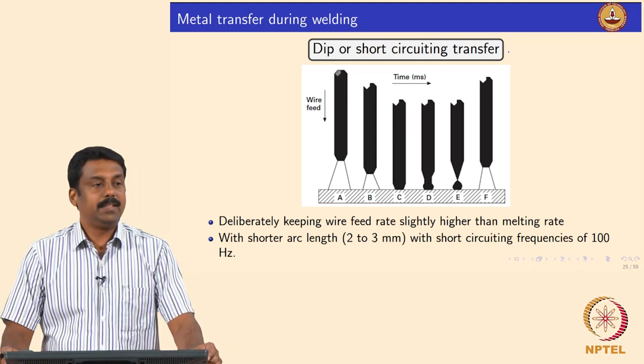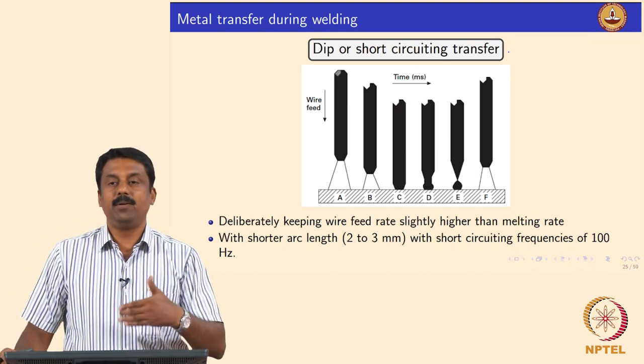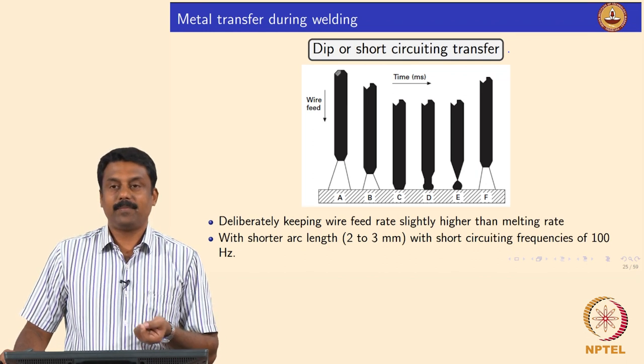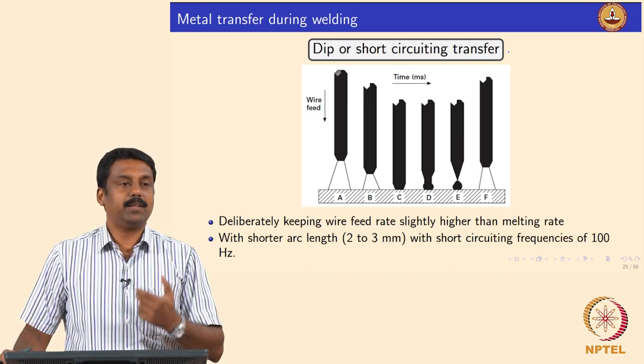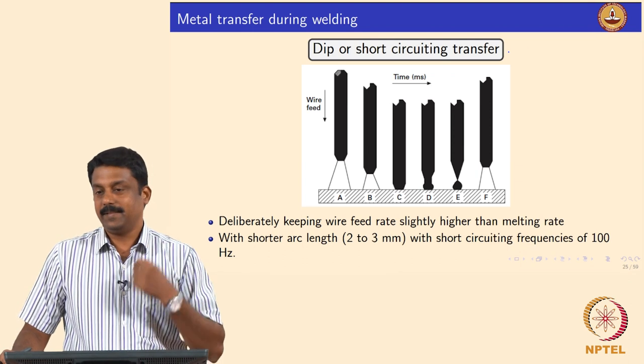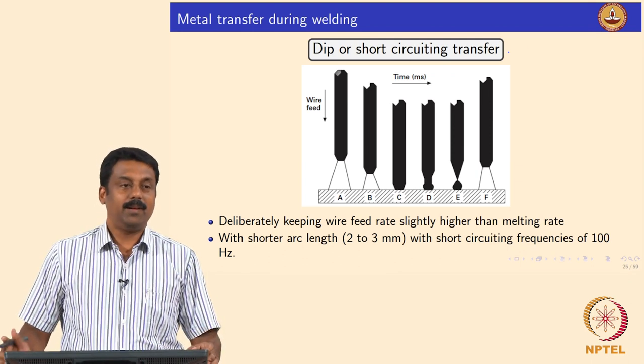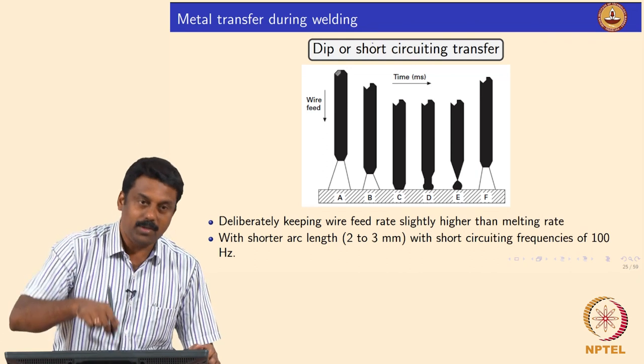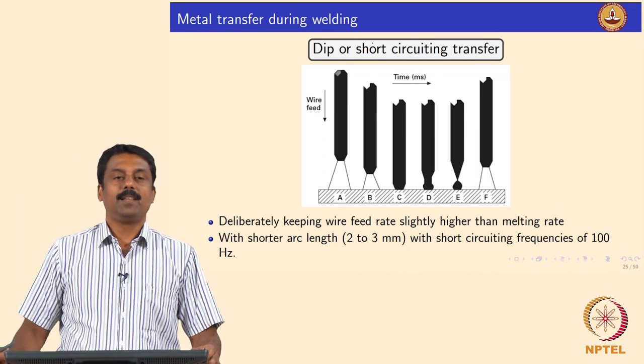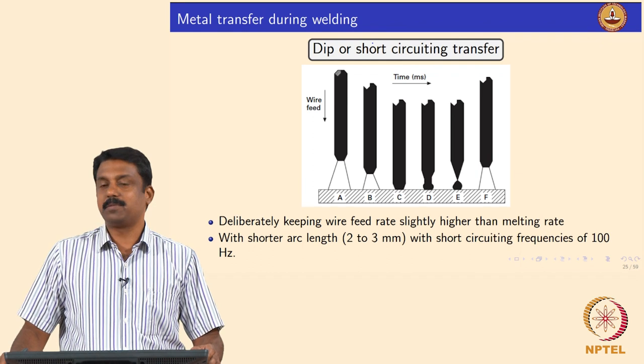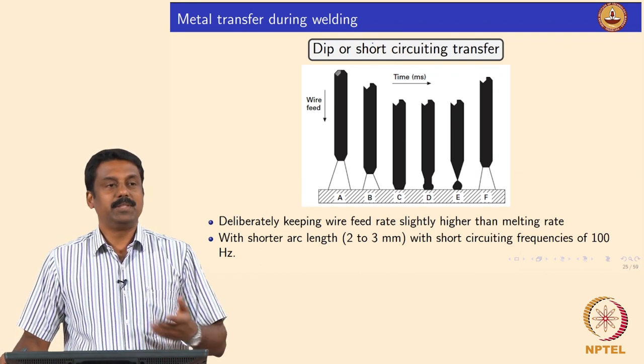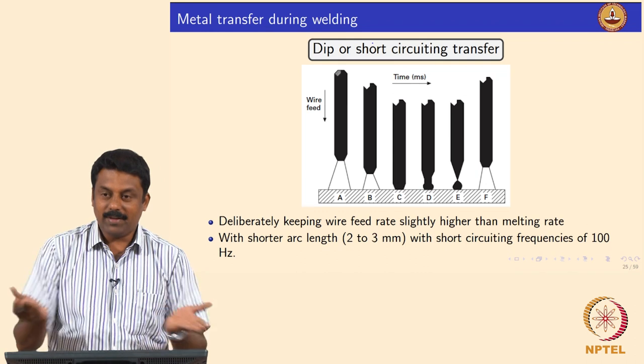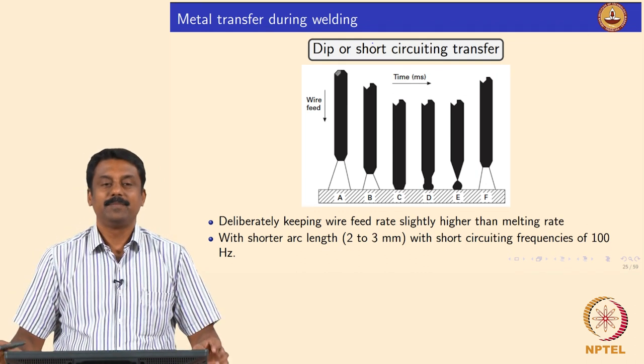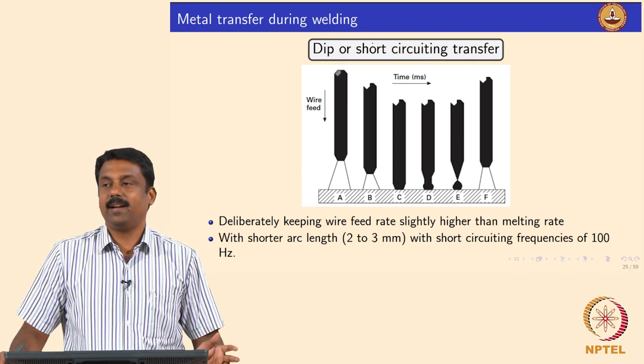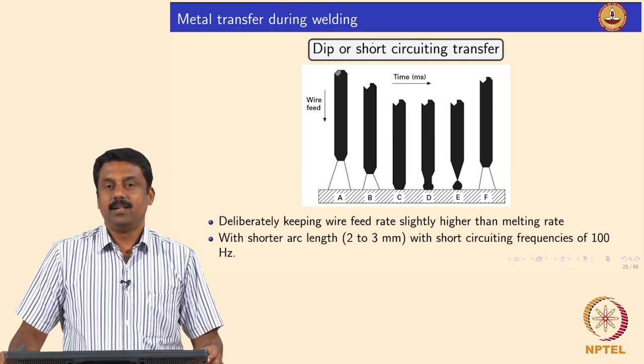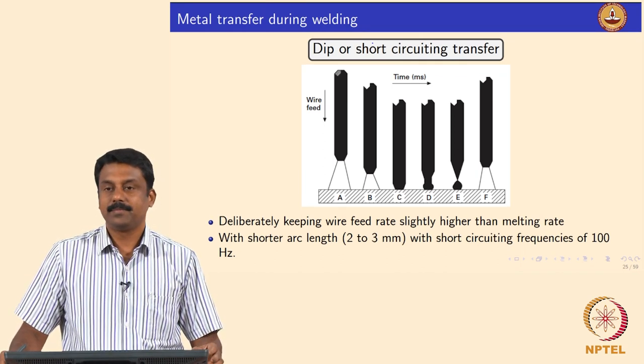So, the other mode of transfer. So far we looked at free flight transfers, and you can also achieve a stable transfer by dip. What do you mean by dip? You can touch the droplet, once it is formed, onto the pool, and when you pull it back, you also change the force balances. You can overcome the surface tension, because the liquid pool's surface tension would make sure that the droplet is detached, right. That kind of transfer is known as dip transfer or short circuiting transfer.